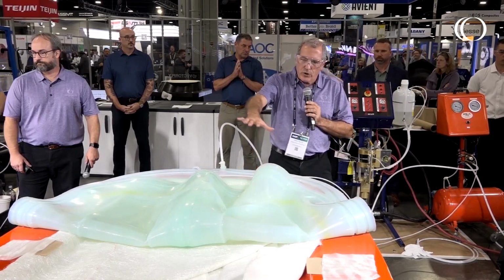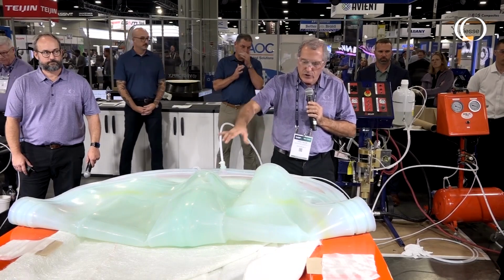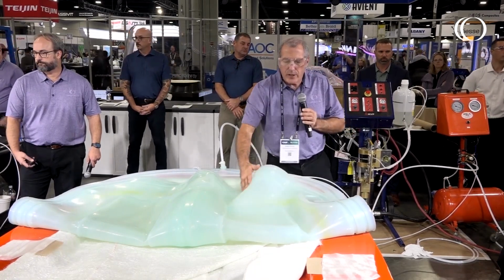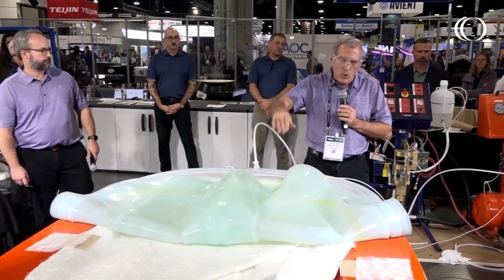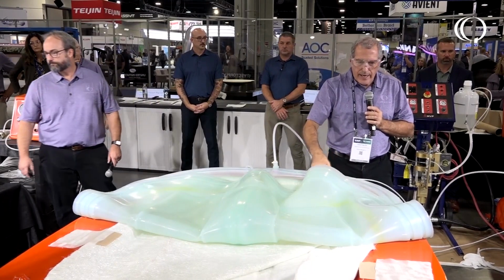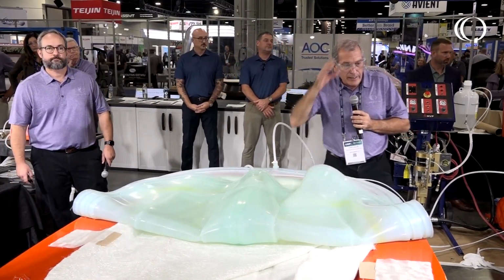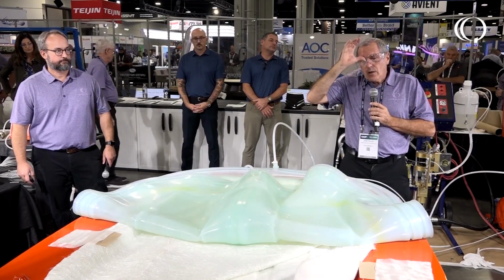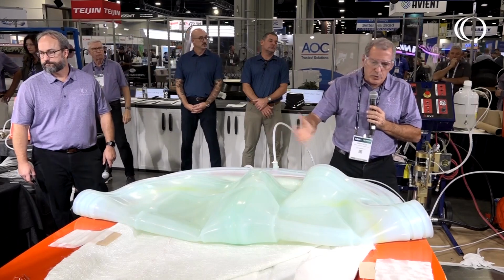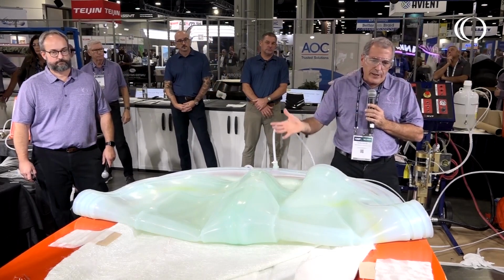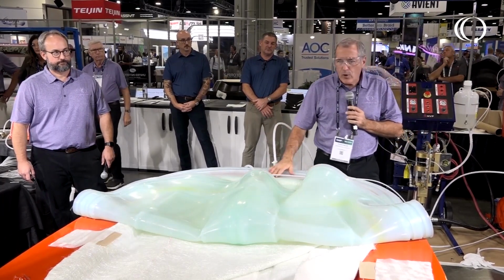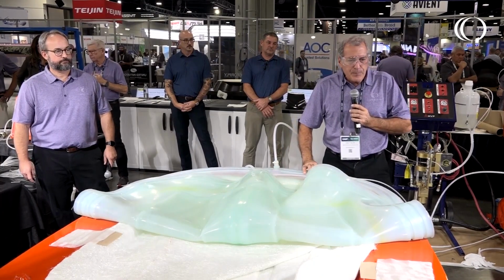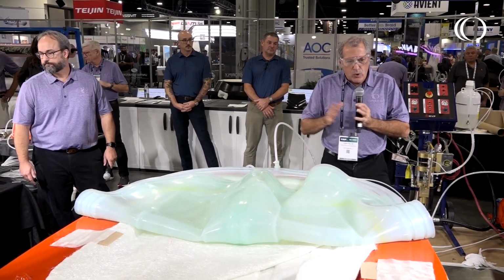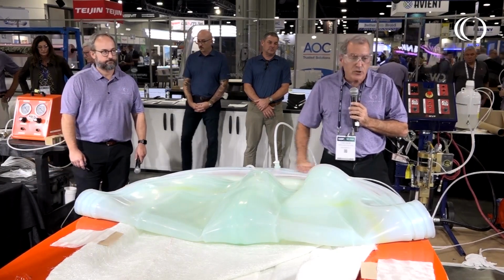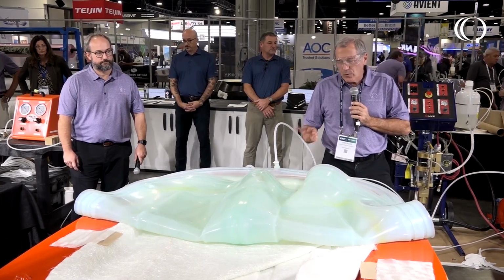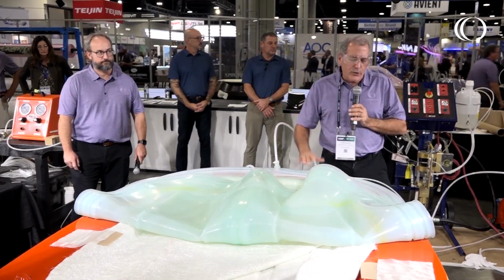As I said earlier, basically we're starting with a profile to build our bag off of, which gives us the net shape of our B surface, so to speak. When we made this bag, we physically had a part in this mold and we sprayed off of that part to make the bag. So we had our offsets in place to make the bag. The process, again, was a combination of extrude material, spraying material, but basically you're spraying layer upon layer and building a thickness. We like to shoot for a nominal 1/8-inch thickness with our swirl material. You go a little less than that and the bag will not hold up as well. You get too much heavier than that and you're really just wasting material. So we found an 1/8 inch, maybe a little north of an 1/8 is an ideal thickness for the material.